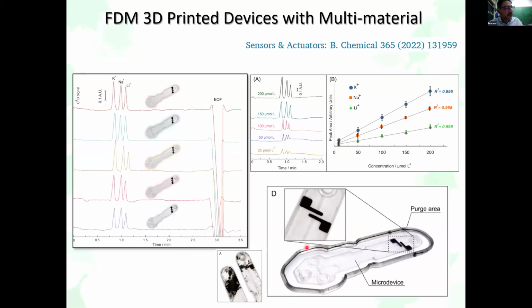And here's another important detail, actually, that Heverson used a kind of purge area to eliminate the residues of the filament that stay on the nozzle, so you can clean and get, as I said, a device without any damage. If you don't take care during the process, you can get this kind of damaged device. You cannot use this.